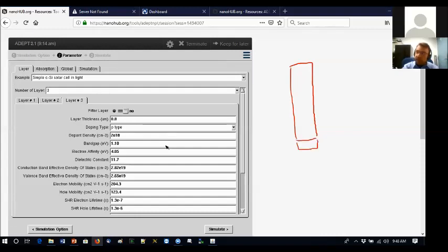We would have a thin layer here, another layer here. So this would be the N plus region, the P region. Now the third layer is also P-type. It's 0.8 micrometers thick. So it's intermediate. It's not as thin as the N plus, not as thick as the P. P is the dominant. And it's also very heavily doped, 2 times 10 to the 18.